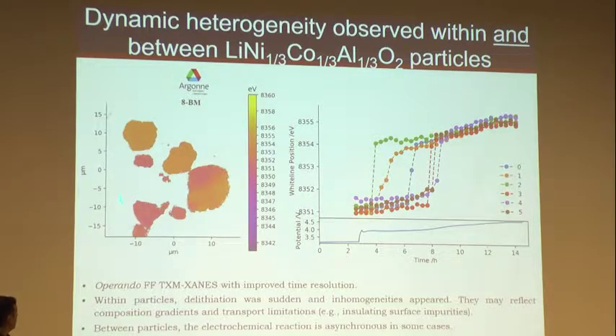And so on the left is a snapshot at one point of the reaction. This was done here at 8-BM, where you can see a particle that has a heterogeneity, where some parts of the particle are more oxidized than others. The other interesting thing that you can do with this measurement is that because we can have multiple particles in that field of view, we can then integrate the overall state of that individual particle. How oxidized, on average, is nickel in that particle? Not locally on those spots, that's what I'm showing on the left, but on average in that particle.